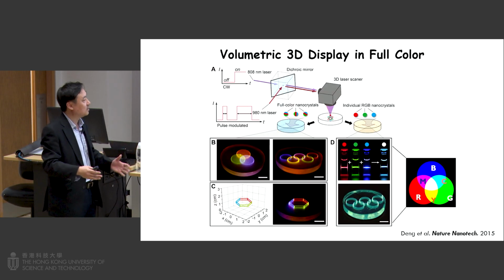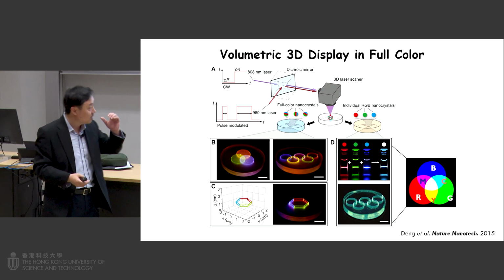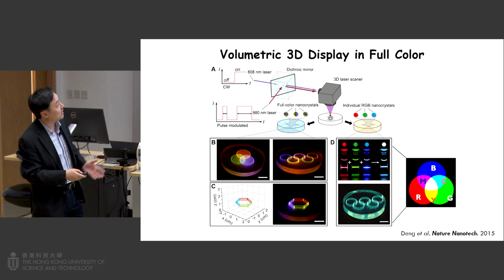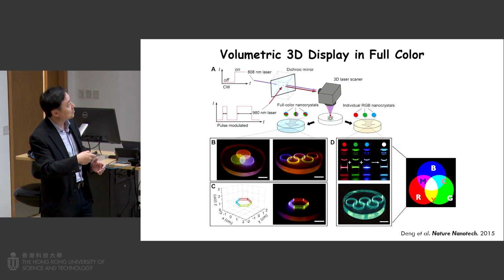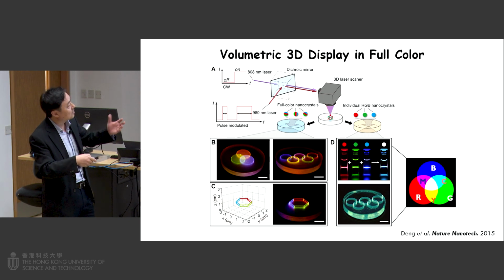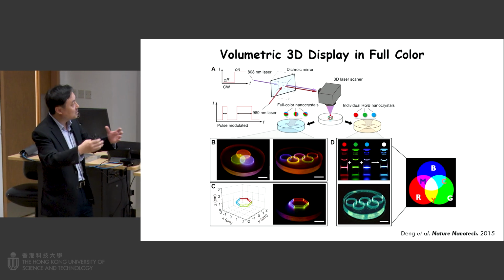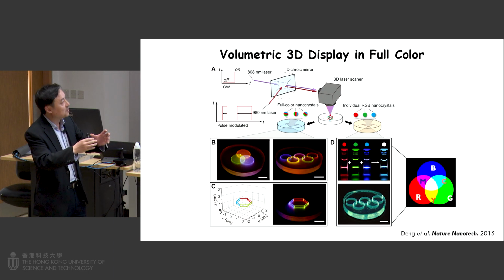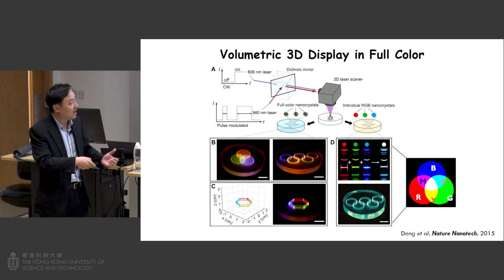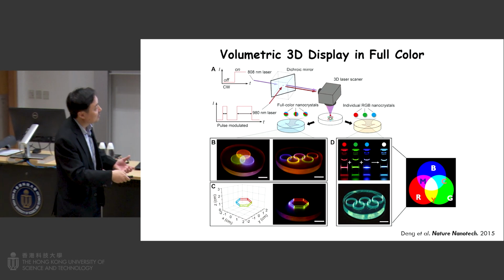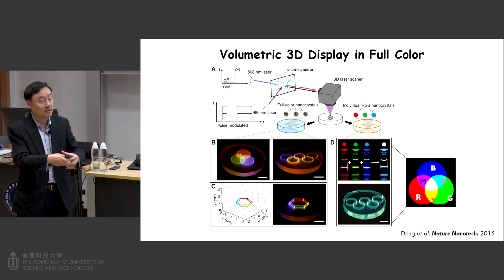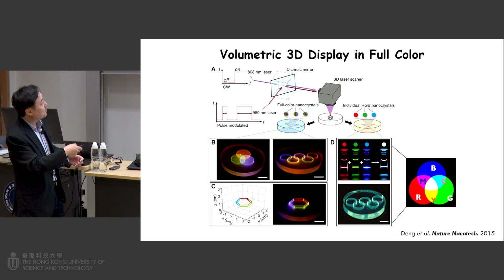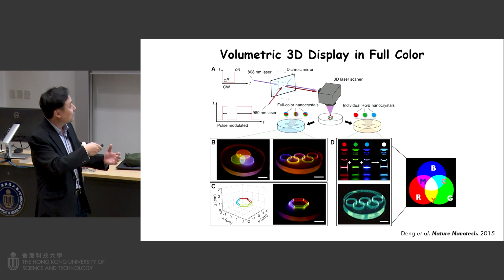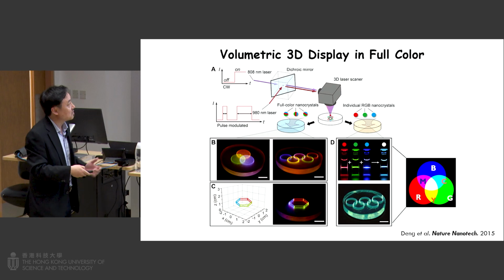So what is useful? Once we have this material, one demonstration is that we can achieve volumetric 3D display in full color. It means that using laser scanning, we can build all these wonderful multiple colors. Compared to the control experiment, if you simply mix RGB color-emitting nanocrystals, we have saturated colors. This is understandable because all the colors are saturated. We cannot control it. If the particles are too close to each other, we actually get a white color. But using our materials, we control the pulse duration, and we can change the color. So this is one capability of these pulse-duration-sensitive materials.